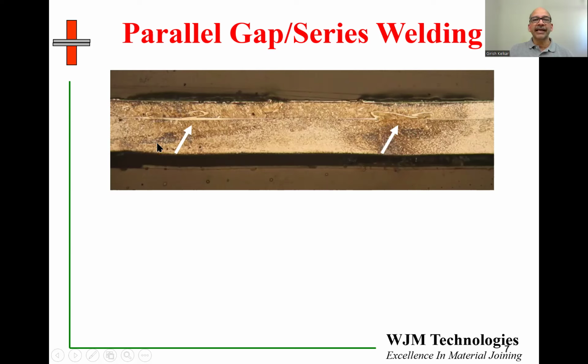You can also see a heat affected zone where the contrast is different. And that shows you that these are 2 separate welds. So the current would have gone down from the top electrode, from the left electrode, into the 2 components, flowed across, and then gone back up.